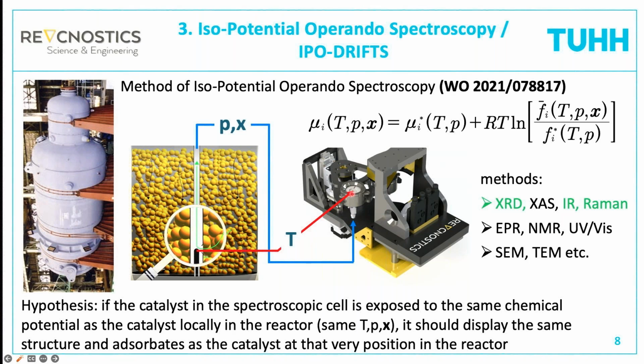And these three quantities, the temperature, pressure, and the chemical composition, determine the chemical potential by the known formulas. So in this way, the catalyst in the spectroscopic cell sees the same chemical potential as the catalyst locally in the reactor. And the hypothesis is now that if the catalyst in the spectroscopic cell is exposed to the same chemical potential as the catalyst locally in the reactor, so same temperature, same pressure, same chemical composition, it should display the same structure and the same adsorbates as the catalyst at that very position in the reactor.